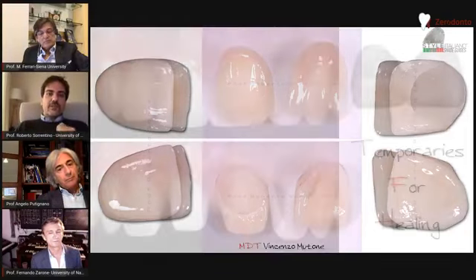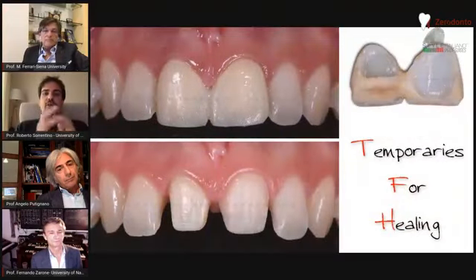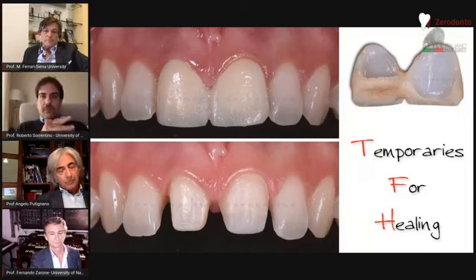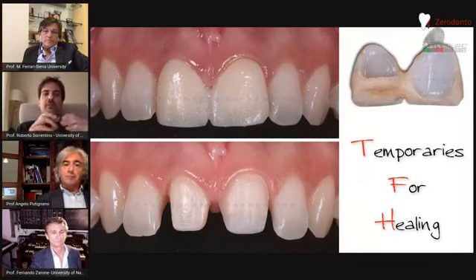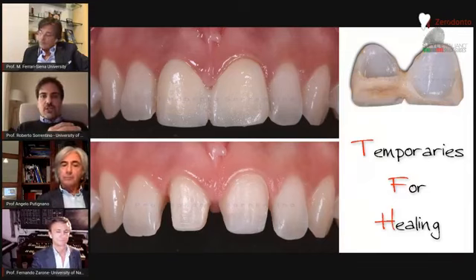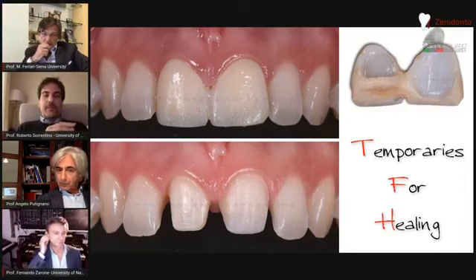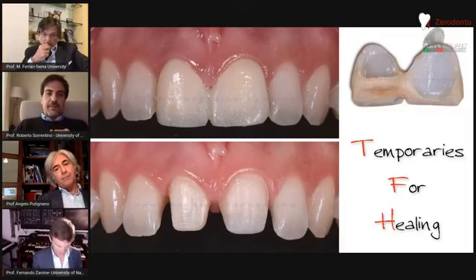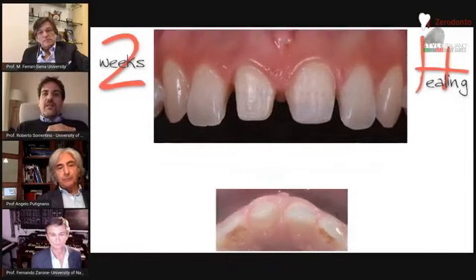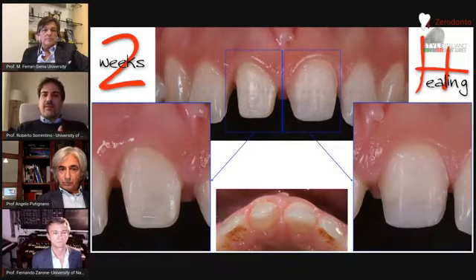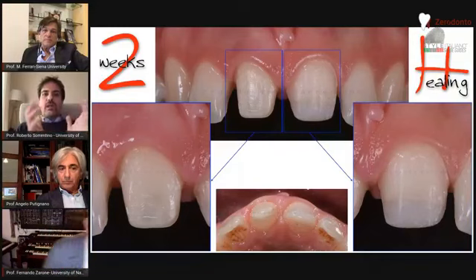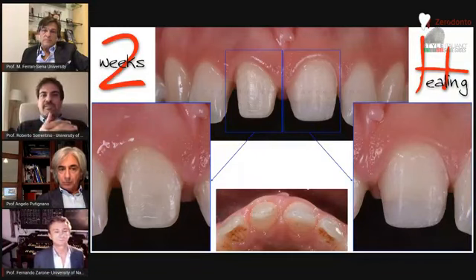And 2 weeks after the final impression, the recovery of the soft tissues was very satisfactory thanks to the precision of the temporary prosthesis that made possible a correct stabilization of the gingivas and filling of the interdental papillas, as you can see. And here you can appreciate the healing of the soft tissues at high magnification with the good color and shapes of the soft tissues, showing the ideal features for the subsequent cementation of the restorations.